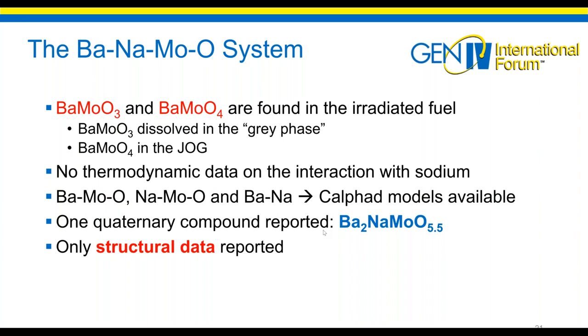If you remember the beginning of the presentation, I was showing you some phases that are stable in the irradiated fuel. The two phases, BaMoO3 and BaMoO4, are found in the irradiated fuel: the BaMoO3 dissolved in the gray phase, and the BaMoO4 in the JOG. However, there is no thermodynamic data on the interaction between these phases and sodium. But we have some CALPHAD models available: barium, molybdenum, oxygen; sodium, molybdenum, oxygen; and barium, sodium.